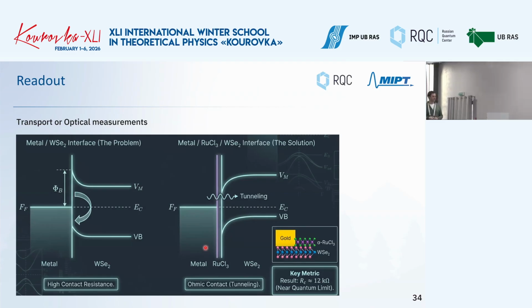We tried, let's say, 1.5 years to combine some materials to repeat something in literature, and with the transport measurements, sometimes we're still struggling. For example, here there is a recipe for WSe2, a material that indeed will work out with ruthenium chloride (RuCl3). But we tried different approaches, and it turned out that this is quite problematic. So the transport properties we cannot easily measure. Now we cannot detect the Mott insulator in the transport properties, let's say.